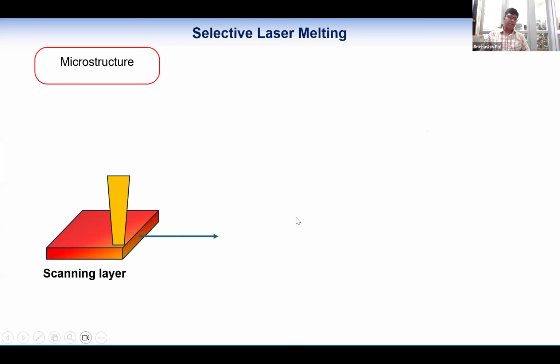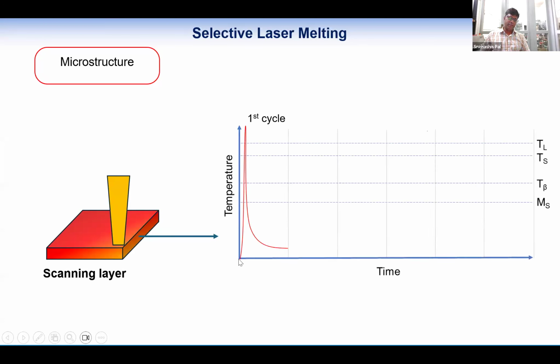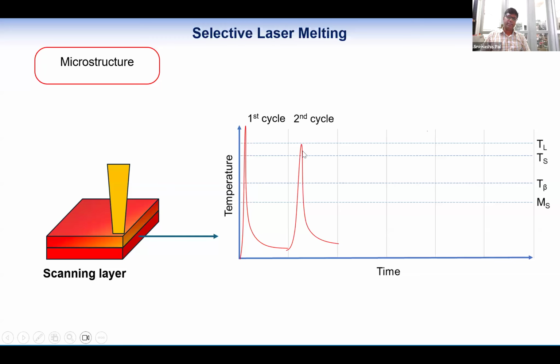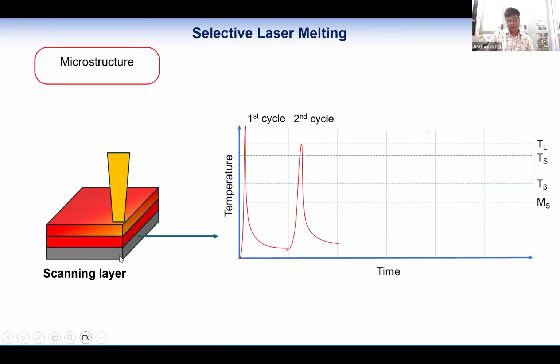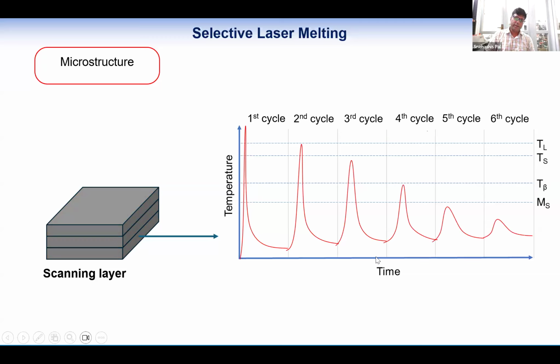So why does this occur? When scanning a layer, heat is generated and goes above the melting temperature, and then it cools down to room temperature. Then the next layer is formed by scanning again, and the same layer is heated up again. It can be more than the beta transus temperature, or maybe below the liquidus temperature. This can occur several times. Again during the third layer, that layer will be heated up again. This is the graph for the temperature: it increases in this way, with several thermal effects.